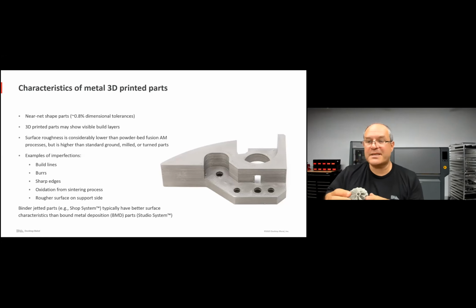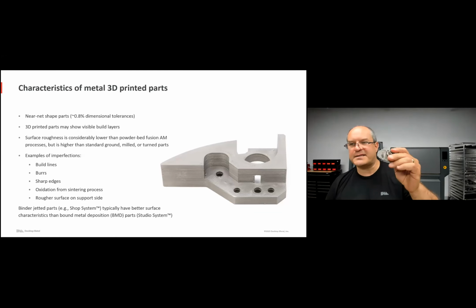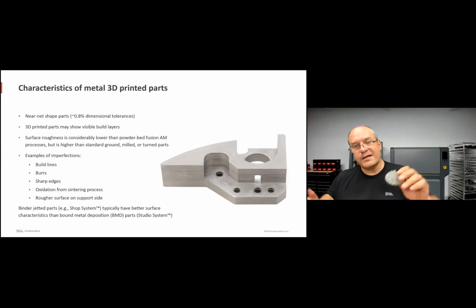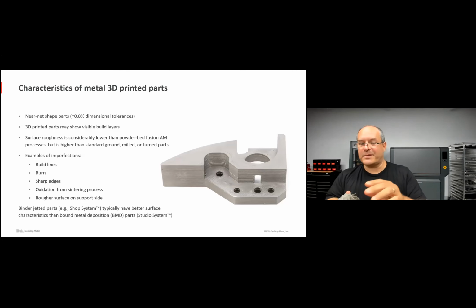There also may be some oxidation just at the very surface, and so literally a couple microns worth, even though you might print it as stainless steel in the furnace, some of the chromium might have evaporated from the surface. And so literally there might be just less than a micron of oxidation, but that's easy to get rid of with, say, media blasting. We'll talk about that as well.